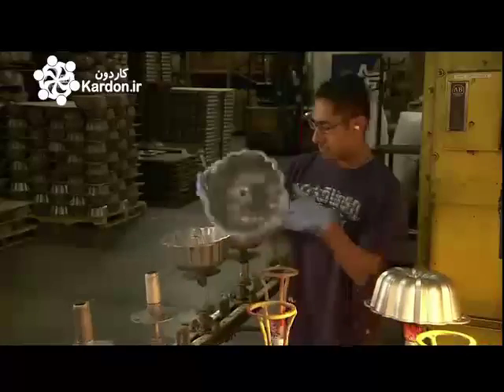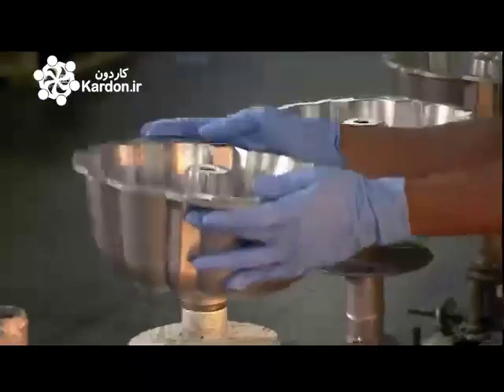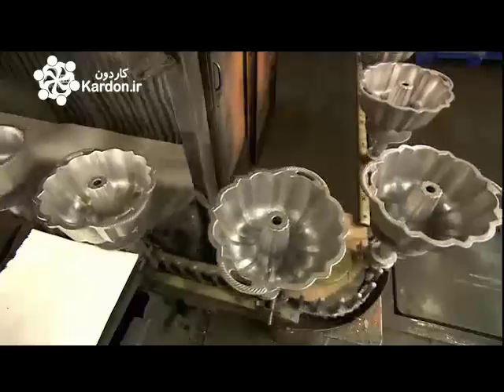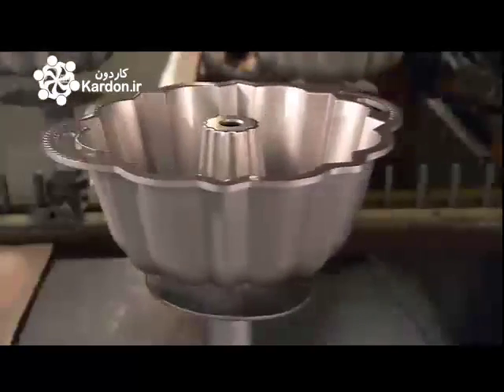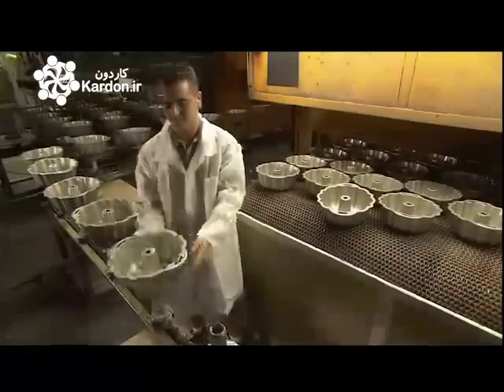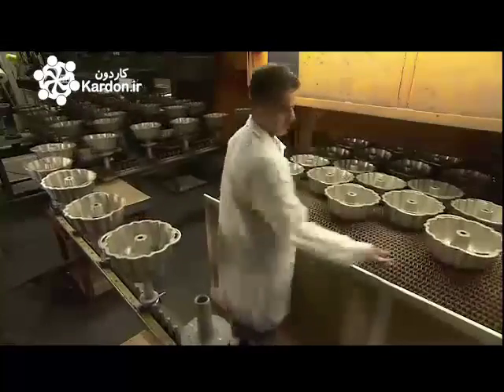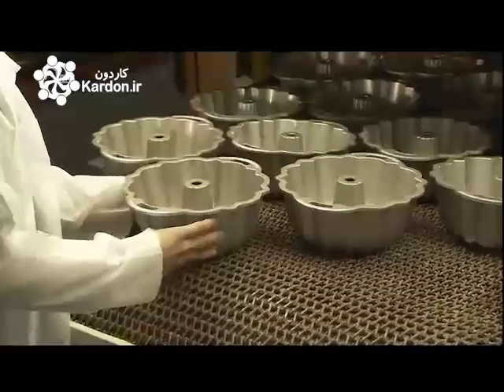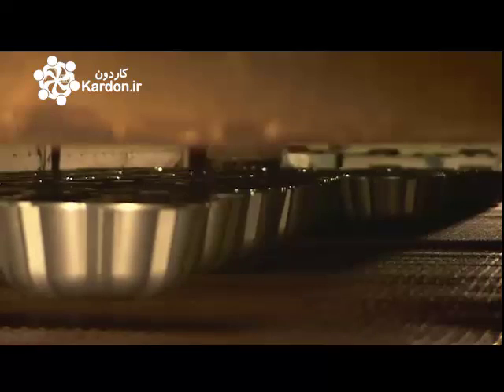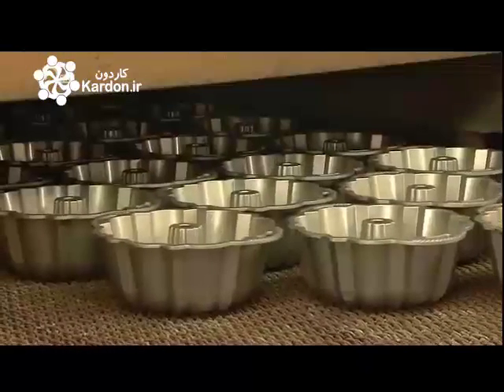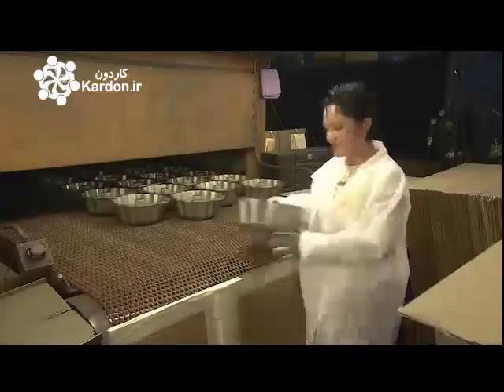The pans are then flipped right side up and sent through another spray line, this time to coat the inside. The interior coating is a food-safe silicone polyester material designed to release the cake easily from the pan. It's similar to the non-stick coating on a frying pan, the difference being that the chemical composition is designed to prevent sugar rather than protein from sticking to the pan. Once more, the pans go through an oven for 15 minutes to cure the coating. Once the finished pans exit the oven, they're inspected for any flaws in the coatings.